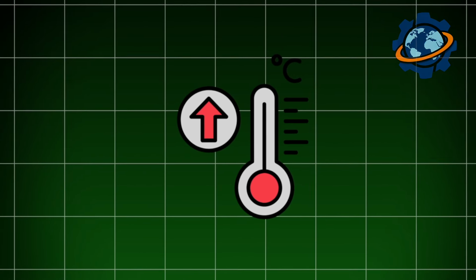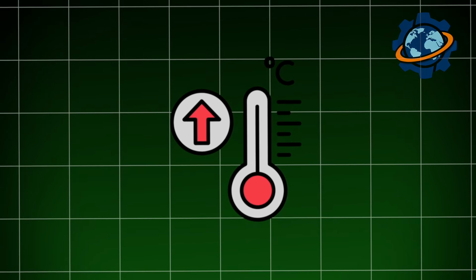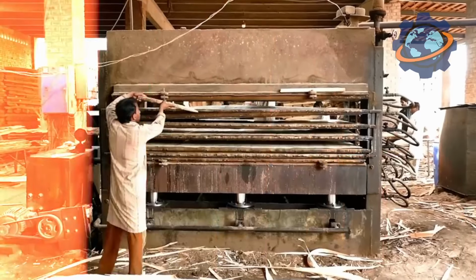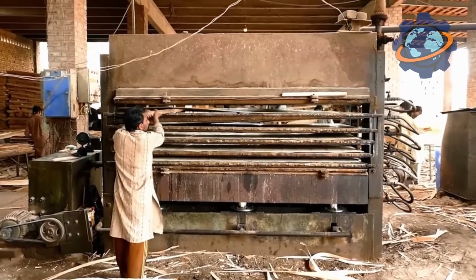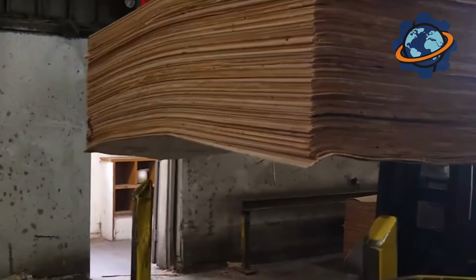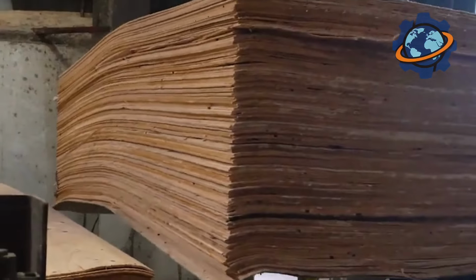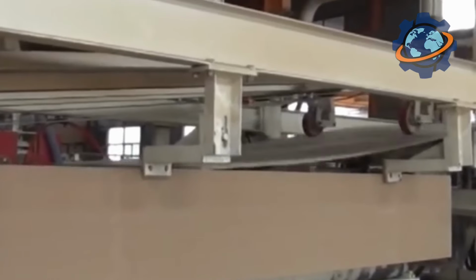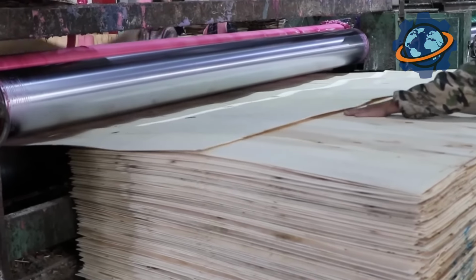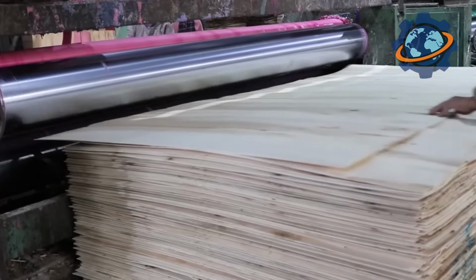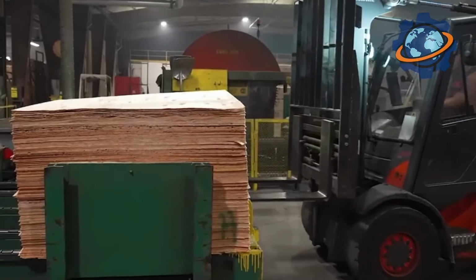Under the influence of high pressure and temperature, the glue polymerizes, penetrating into the pores of the wood and permanently bonding the layers into a single, incredibly strong monolith. The pressing process lasts for several minutes, after which a finished plywood board is born. Hot sheets of plywood come out from under the press and are stacked for gradual cooling. This is important to avoid internal stresses in the material.